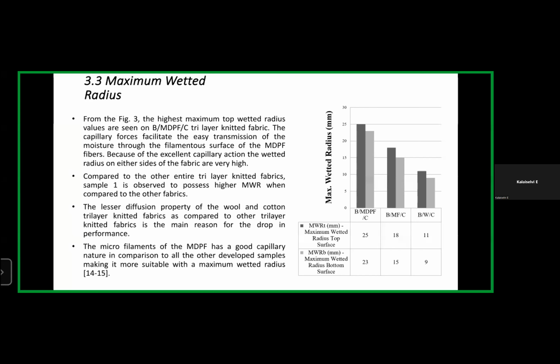The wetting radius. For the wetting radius also, the highest maximum top wetting radius is seen in bamboo microdenier polyester filament and cotton tri-layer knitted fabrics. This is because the capillary forces facilitate the easy transmission of the moisture through the filamentary surface of the microdenier polyester filaments. Because of the excellent capillary action, the wetted radius on either side of the fabric is very high. Compared to all the other tri-layer knitted fabrics, sample 1 is observed to possess a higher moisture wetting radius.